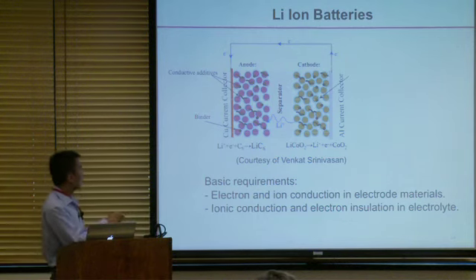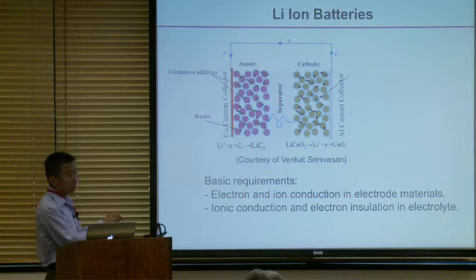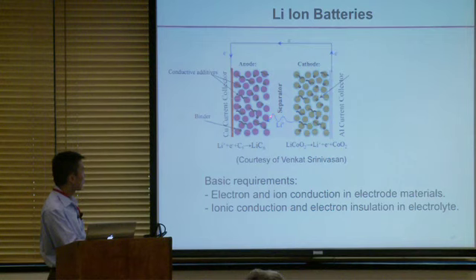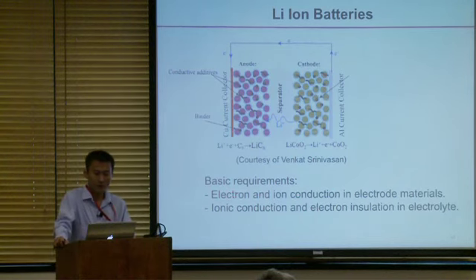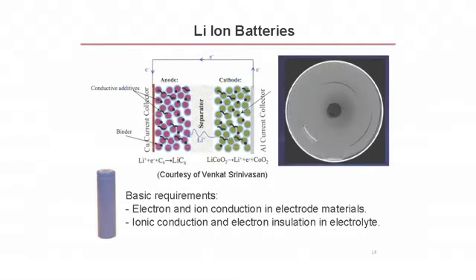They can be conducting. You need a separator to separate these two electrodes to prevent shorting. This separator also needs to let the lithium ions move through, so you put in the liquid electrolyte inside. So at the end, this is the ionically conducting component. And the electrodes, since you need the lithium to go into the structure of the materials, need to be both electronically and ionically conducting. And then after you have that, you roll this up into a jelly roll. This is the typical form factor we use. This is the cylinder cell that shows up like this at the end.